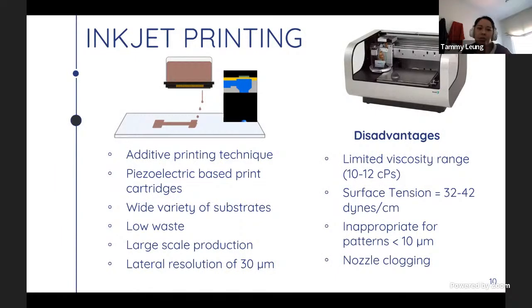Inkjet printing itself is an additive printing technique that deposits droplets one by one onto any given substrate, which can create patterns down to tens of microns. It functions through the use of a piezoelectric actuator that, when a voltage pulse is applied to the reservoir walls, contracts and then releases the ink through the nozzle itself. Simultaneously, the print head laterally scans the substrate, printing the pattern line by line. The advantages of this technique include the fact that any type of substrate can be printed regardless of whether or not it is flexible or rigid, and it allows for a very low waste of ink in the end.